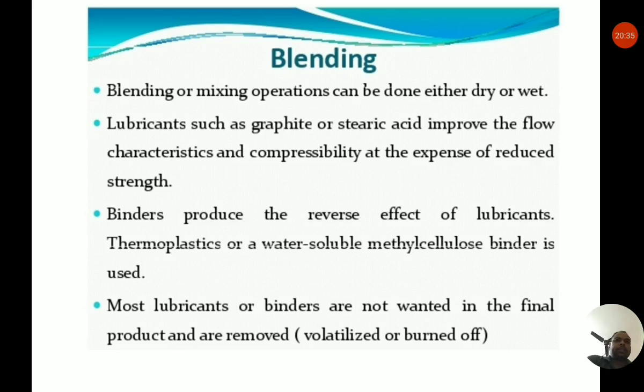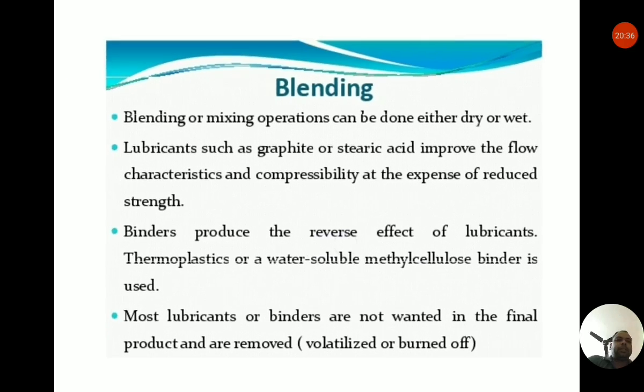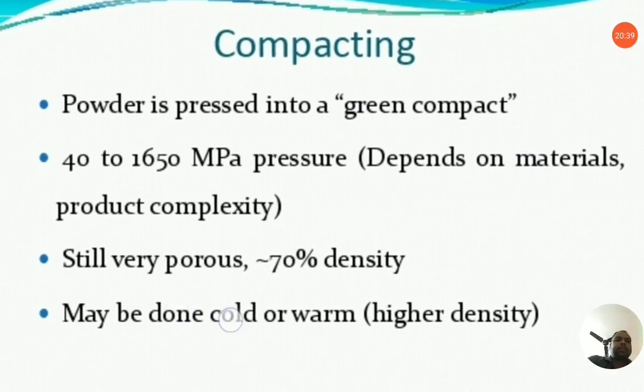So next we have the compacting. The powder is pressed into a green compact. Okay, and the pressure generally is 40 to 1650 MPa, depending on materials as well as product complexity. Still very porous, 70% density you can see over here, may be done cold or warm, with higher density when it is warm. Okay, so actually what happens in compacting, loose powder is compressed into a shape known as green